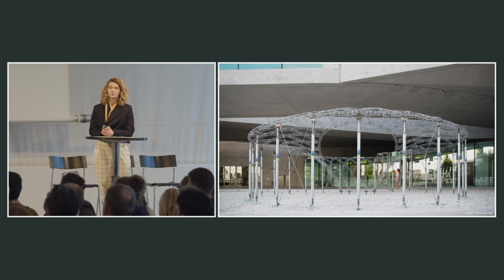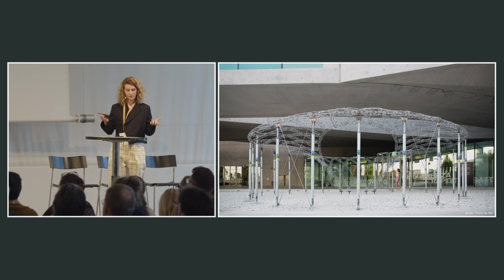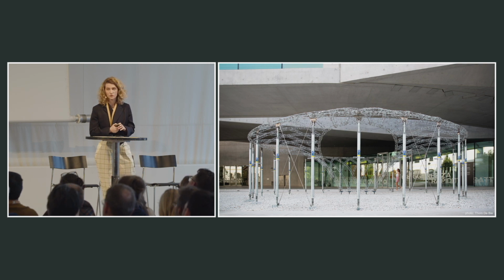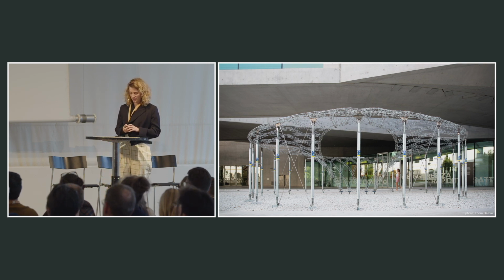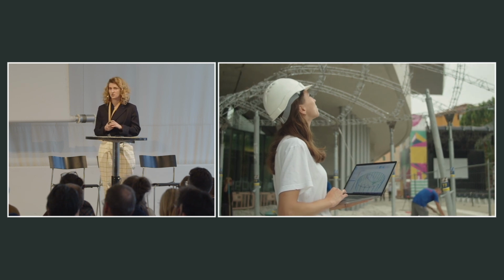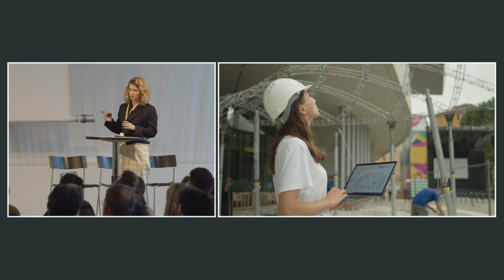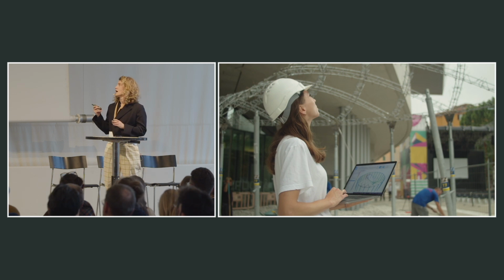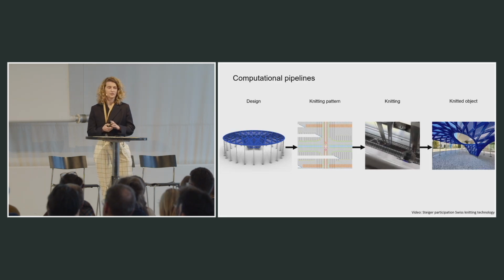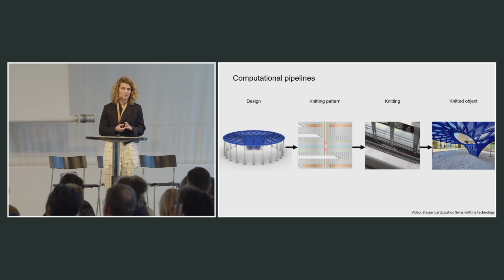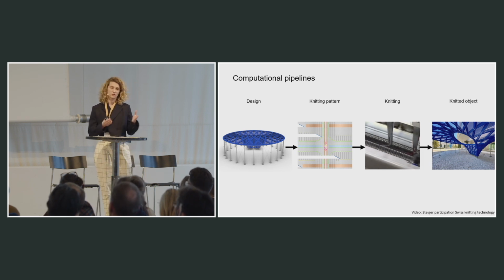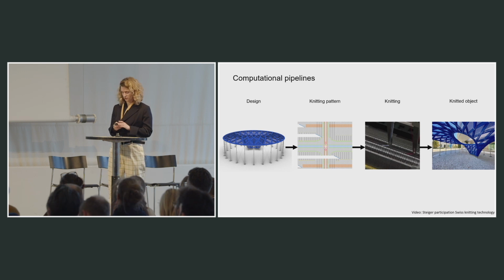So in our first stage, we had this structural grid shell that becomes reinforcement within the structure. And we took advantage of the fact that we have a little bit of time and decided to take that time to measure the constructed geometry such that we can build a fitting textile, not for the design itself, the original one, but for the measured in structure, because we had a computational pipeline that allowed us to do this relatively fast, meaning that we didn't need to start production in parallel with having built the previous structure.